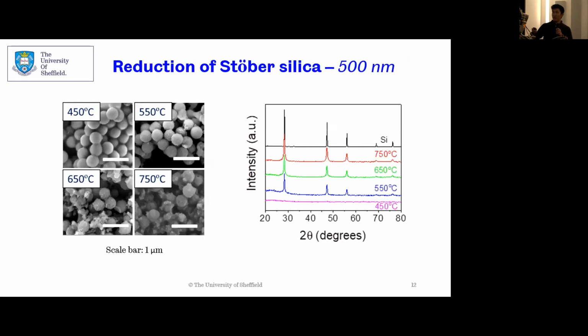So here on the left, I've got SEM images of particles that have been reduced and washed. At 450 degrees Celsius, nothing has happened to the particles, so no reaction can be seen. But from 550 and above, the SEM images show that something has happened, some reaction. And on the right, you can see XRD data. The 450 degrees Celsius does not have peaks for silicon. So this is the standard for silicon here. These are the peaks that match up with it. 550 and above, crystalline silicon is there.